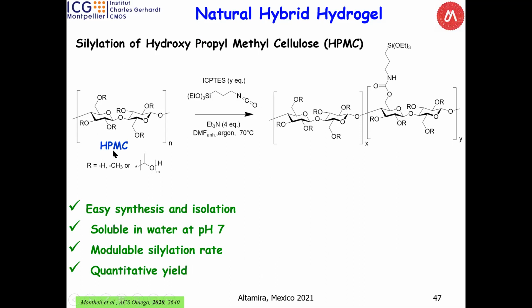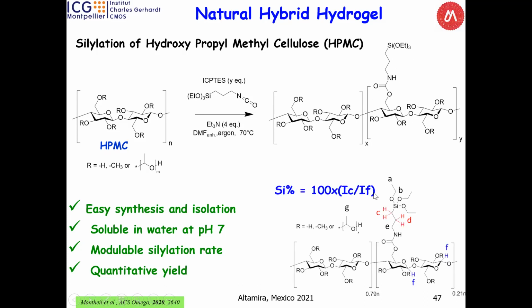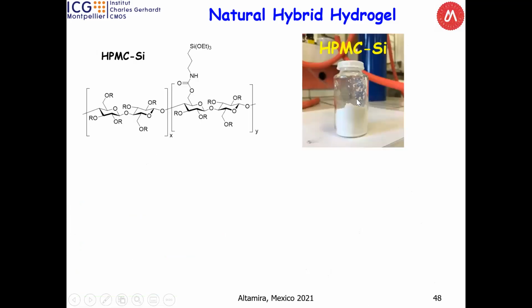So we took HPMC reacting with isocyanatopropyl trialkoxysilane, and it was possible for us to control the silylation rate just by changing the ratio between ICPTES and HPMC here. And as before, by NMR you can estimate the silylation rate, just by integration of this proton and this one, C or D, the red one or the blue one. You make the ratio and you obtain your silylation rate. And we isolated it without any problem, with a quantitative yield, as a powder, and it's stable for several weeks at room temperature without any specific conditions.